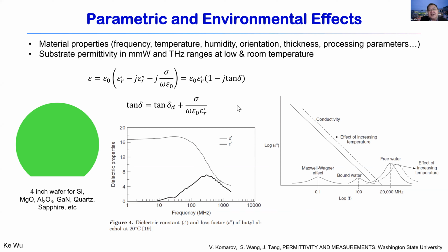So in this case, you see that the loss tangent will be described very well by this complex term as a whole. The dielectric is a frequency independent portion of the loss tangent. Usually it's negligible, and we don't really consider it too much. But as a generalized measurement term, we can consider it as a whole, because we always measure from input to output. We don't care about what's inside.